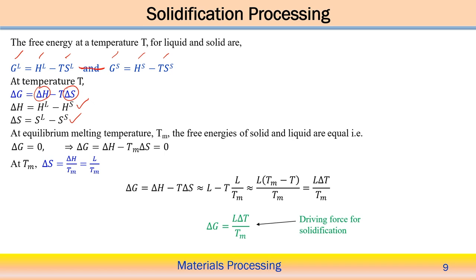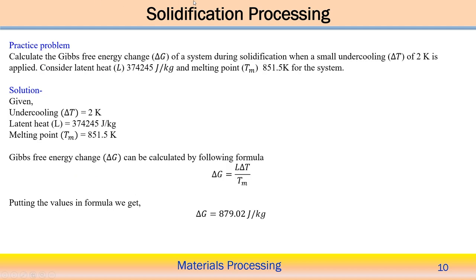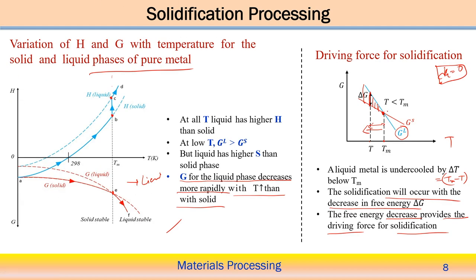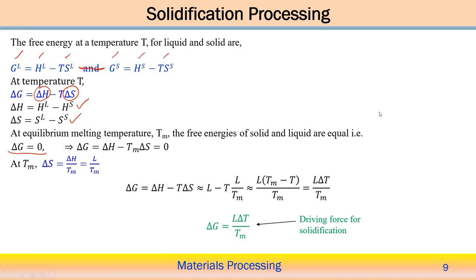Now, at the equilibrium melting point temperature Tm, basically where solidification occurs, the free energy of the solid and liquid phase are equal. So here you see delta G equals 0 at the equilibrium melting temperature. Making it 0 gives the equilibrium position, but overall delta G equals delta H minus Tm into delta S.